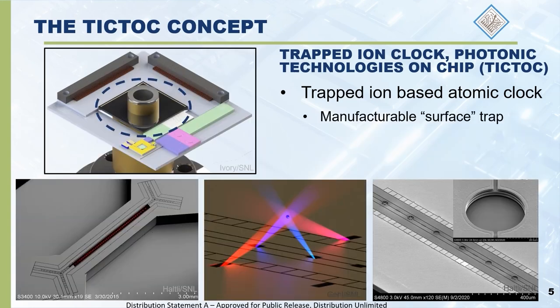The heart of the system is a surface ion trap, an example of which is shown in the left corner. Surface ion traps are quasi two-dimensional devices that can store and probe numerous ionized atoms. They are compact, usually only a few millimeters on the side, manufacturable with current semiconductor technology, repeatable, and precise. In our case, trapped ytterbium ions serve as the frequency reference for our clock. By probing the ions, we gain information about and feedback to the wavelength of our most precise laser, the so-called clock laser, which serves as our oscillator. Most importantly, our surface trap has built-in light delivery systems and integrated single photon detectors, significantly reducing the hardware needs.